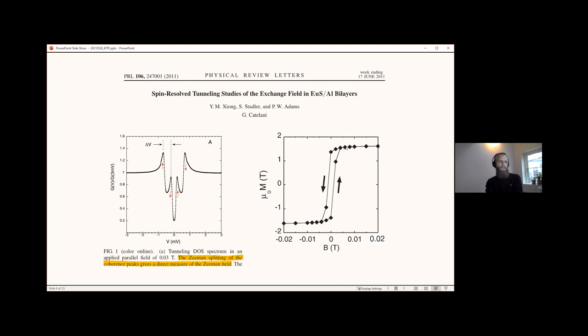And then they found this hysteretic loop, depending on the sweep direction of the external field. Mainly what I'm trying to show here is that the remanent magnetization that they found at zero magnetic field exceeds one Tesla. So this looks like an interesting system to study. As I showed before in the tunneling spectroscopy data, to spin split and bring the subgap states to zero energy, we need magnetic fields of around one Tesla. It seems like europium sulfide in combination with aluminum can provide it to us.